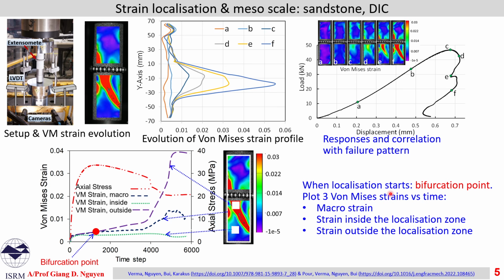And this is telling us something. This is bifurcation, beyond which we don't have a single stress-strain relationship anymore. Stress can be very similar, but strains, as you can see here, become very different. The macro strength, the volume average one, and the strains inside and outside the shear bands are very different.